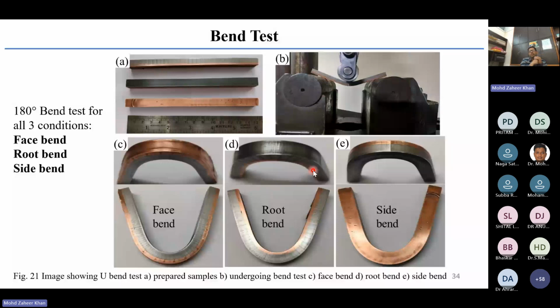This is the result of the bend test that I have described, and you can see over here the material that in all the face bend, root bend, and side bend, it could be bent into almost an 180-degree bend. Of course, before it being formed into a 180-degree bend, it slipped out of it. So this is the extent of almost 160 degrees of bend that has been created, and even after bending, the copper and steel are inseparable. They are still remaining intact.